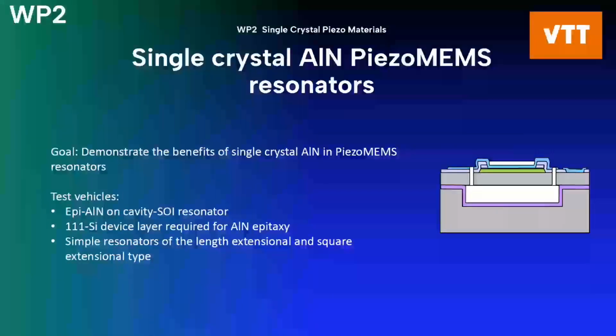Then we move to work package 2 on the single crystal aluminum nitride-based piezo MEMS resonators. So our goal is to demonstrate the benefits of using single crystalline aluminum nitride in piezo MEMS. As test vehicles, we use SOI and cavity SOI based resonators with the 111 oriented silicon layer, which is required by the epitaxial growth of aluminum nitride, and make simple resonators of the length extensional and square extensional type. The cross section is schematically shown there, the green layer being the epitaxial aluminum nitride.